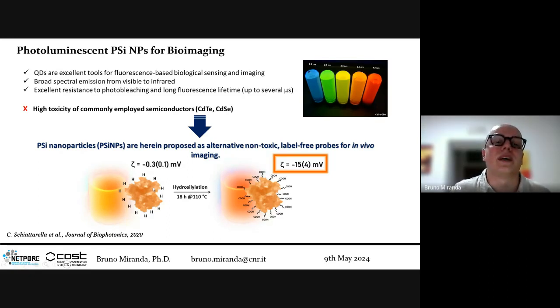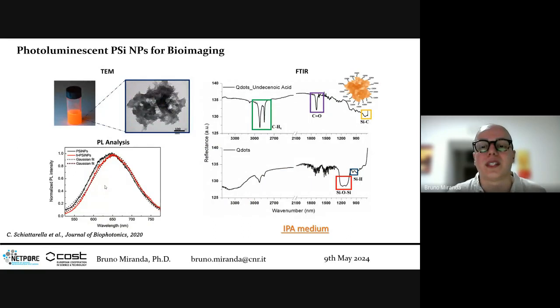Commonly employed semiconductors such as cadmium selenide and cadmium telluride are very toxic for in vivo applications. Instead, porous silicon is highly biocompatible and biodegradable, but its main limitation is its instability. So we developed functionalization strategies to passivate these nanoparticles and stabilize their photoluminescence.